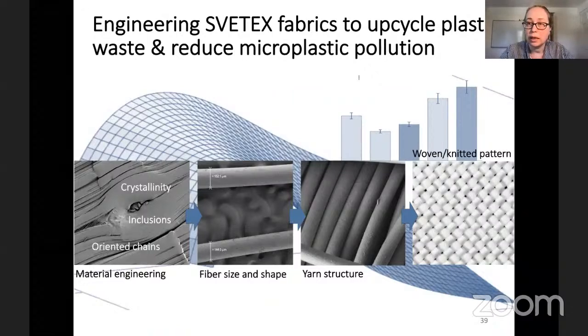So what we do instead, we engineer monomaterial textile platforms that are all made from polyethylene with maybe some addition of inorganic particles that can be very easily separated at the end of the life cycle, mechanically and by centrifugation. But otherwise, we just engineer only one material, one polymer, and we do all the changes through changes of the morphology, size of fiber, shape of fiber, composition of the fabric.